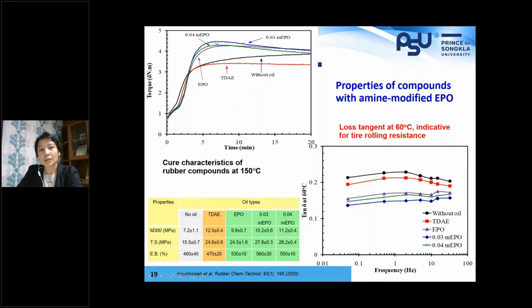We can see a higher maximum torque here, and this maximum torque can be related to cross-link density in the vulcanizate. So by having better cure, we see a lower tan delta at 60 degrees by using this amine modified EPO. So for tire application, in terms of dynamic mechanical property, by having modified palm oil, we can see a better elastic response without a loss in mechanical properties.